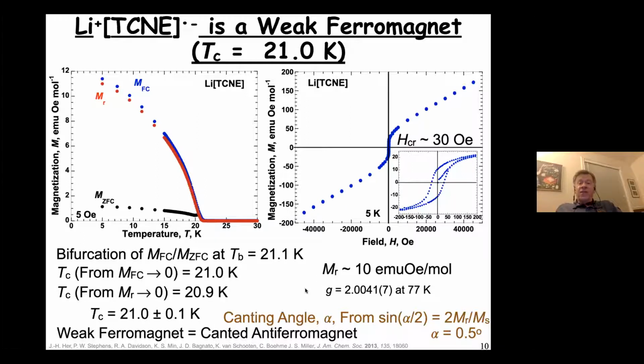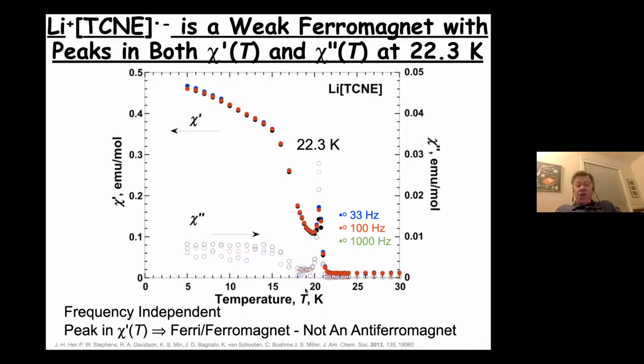We've eliminated the possibility of it actually being an anti-ferromagnet, because if we look at the AC chi prime and AC chi double prime as a function of temperature, we see absorptions for both of them, whereas you should not see chi double prime of T if it's in fact an anti-ferromagnet. Both are frequency independent, and you can see this pronounced absorption around 21, 22 degrees Kelvin. So we've characterized this material as a weak ferromagnet by many different magnetic measurements.